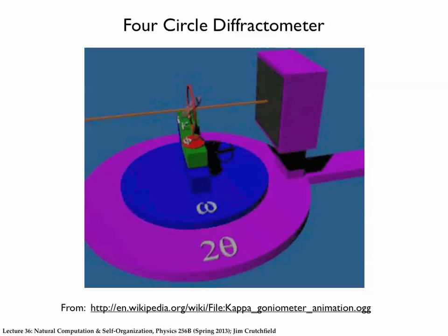Last time we sort of thought about time, although we didn't really specify that, but when I said frequency, it made it sound like time. Here we really are looking in terms of space, but it's the same thing. There's no mathematical difference. So we're going to have these stackings of layers as they go up, and they can either be A, B, or C. And so our correlation functions are going to look a little bit different. We're going to have correlations between layers. We won't just have either like or different. We'll have to say, does this layer go from an A to a B, which we'll call a cyclic rotation, separated by some distance? Or does it do the opposite, or are two layers separated at some distance the same?